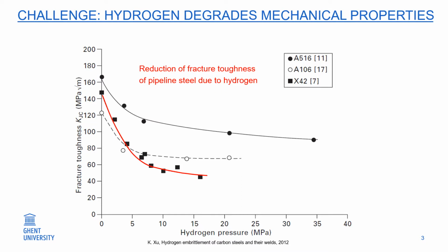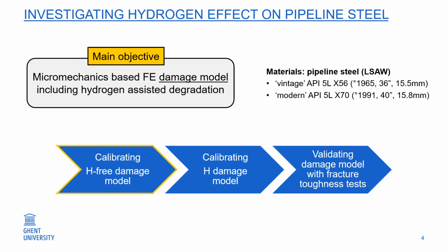However, there is a well-known problem when hydrogen comes into contact with steel. Hydrogen degrades the mechanical properties of pipeline steel significantly, which is often called hydrogen embrittlement. This figure illustrates in red the reduced fracture toughness of a certain pipeline steel due to hydrogen gas. This is why it's highly relevant to investigate the effect of hydrogen on pipeline steel.